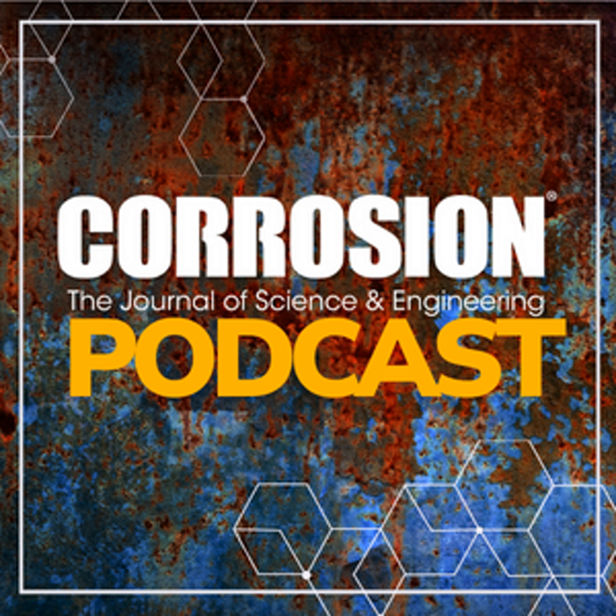Okay. Well, thank you for that. Yes, if I may summarize some of the major features, I think it was very exciting to make a direct observation of the chemical species, especially hydroxide ions and chloride ions on surfaces, to be able to prove that there is really a competition between adsorption of hydroxide and chlorides, with chloride gradually winning the competition. And this increase in chloride concentration explains the fact that we go, in time, from localized corrosion to a more general corrosion.